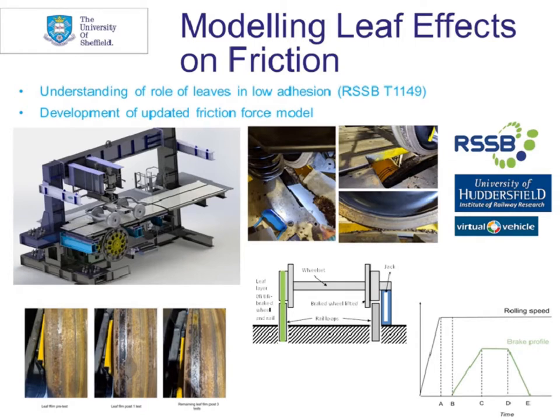So we did some extensive testing on the University of Huddersfield's nice full-scale rig to generate initially leaf layers. You can see them here being grown as we feed leaves into the interface under low speed. See here the leaf layers growing on the wheel in the bottom left-hand corner. Initially bright brown and crusty, and then they become that more familiar black colour after you've carried out some braking events. So we set up the rig to do braking. There's a tread brake bogey on the rig, so we had to jack up one side so we could brake there and then not brake on the other side where we're generating our leaf layers.